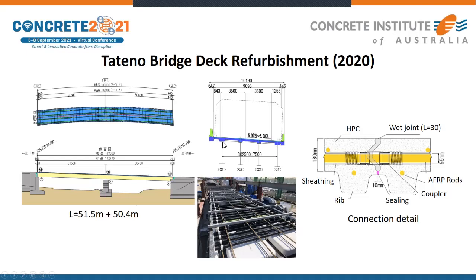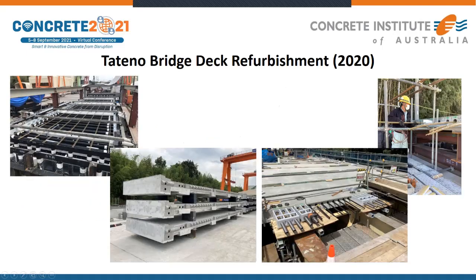And we remove the old reinforced concrete deck and rebuild the non-metallic deck like this. This deck is reinforced longitudinally, and also transversely, by using aramid fiber reinforced plastic. And also we have a very small gap to join the two segments. And these are the photos of the new deck. Before the concreting, you can see the transverse aramid rod, and also this is a segment. And this is the tensioning of the longitudinal aramid fibers by using temporary rods. And this is installation of the aramid fibers into the non-metallic deck.